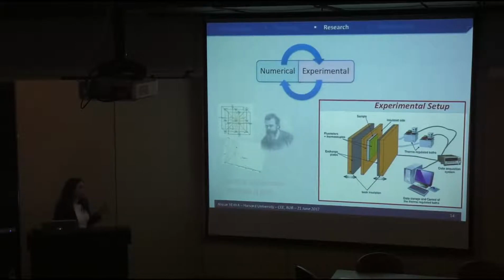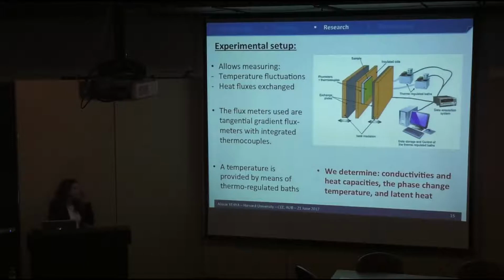We'll talk a little bit about the experimental setup that we've been using in the lab in France. Here is the sample that we've talked about. This is the plexiglass. This sample is insulated, and it's put between two exchange plates where we can control the temperature through thermoregulated baths to control the temperature of the phases.